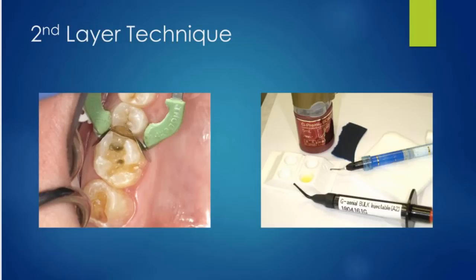So you have a proximal box that's more than 4 millimeters deep, and so now if my curing light gets more than 1 millimeter away, or if there's an undercut in that preparation, I'm not going to get full polymerization and be more prone to micro leakage. So we're just going to do this one in 2 layers.